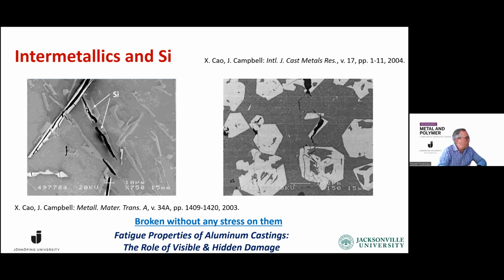It's opening up because these particles have precipitated on existing bifilms. So they are cracked to start with. The cracks are not happening because of a tensile stress. We see the crack because of a tensile stress in fatigue failure, but even in this example, there is absolutely no tensile stress, and we can see how damaged the metal is.